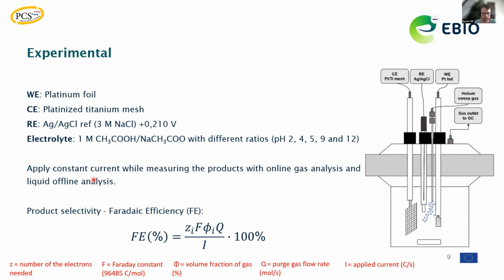So what we studied then is the applied current density, and we measured online the gas phase components that are produced, and of course we also did a liquid phase offline analysis to really understand what products are obtained in Kolbe processes. Just to remind you, Faraday efficiency is obtained by knowing the applied current density, the volume fraction of our gas, and the purge rate of our gas, and of course we need the Faraday constant and the number of electrons involved in the process.